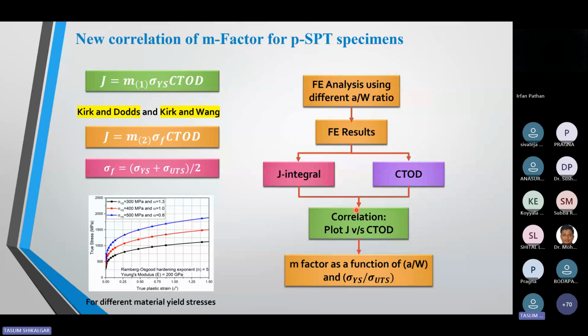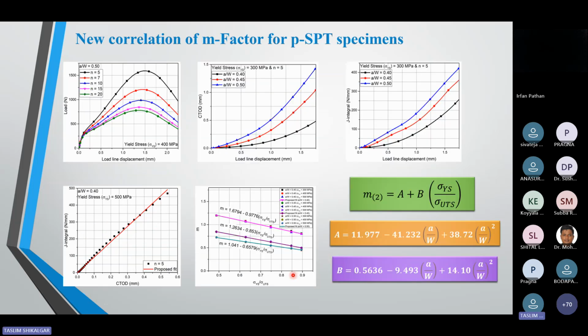And with the help of this correlation, this plot, I generated one M factor correlation, which is a function of a/W. This is a non-dimensional number, and this is sigma yield stress divided by sigma UTS. This is also non-dimensional, because the M factor is also a non-dimensional number. So here I solved multiple simulations for different N. I'm just giving one example for a/W 0.5. If my N is less, I'm getting the maximum peak load, and if my N is more, I'm getting less peak load. And this is just for one yield stress, 400 MPa.